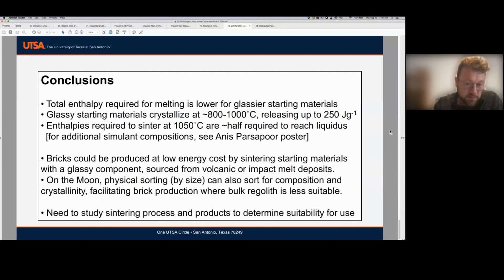And our key conclusions here are, first of all, that bricks can be produced at a relatively low energy cost by sintering, as long as the starting material has about 50% glass or more. That glass could be sourced from volcanic or impact melt deposits, or could simply be achieved by physical sorting, like just sieving and separating out the finer size fraction. The other caveat here is that we've just studied the thermal properties and the energy required. We have not actually made bricks through the sintering process, so I make no guarantees that it's actually going to produce useful construction materials yet, but it certainly saves on energy costs. So if it does work, that'd be great.